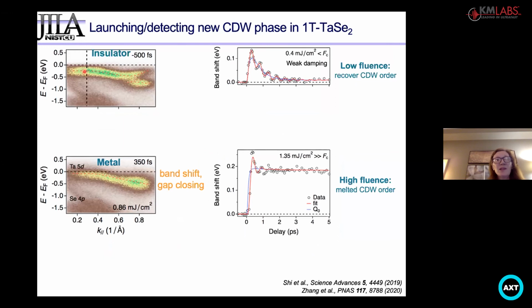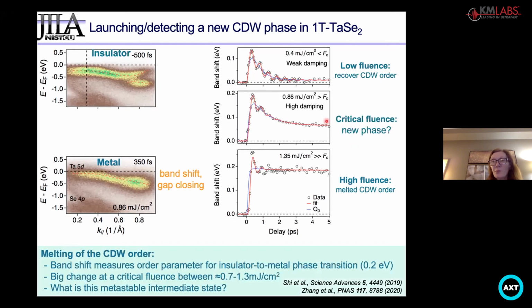So in the insulating state, there's a band gap, and if you take the material and you excite it, you see these characteristic oscillations, and that corresponds to that breathing mode of the Star of David. If you heat the material then with a femtosecond laser, you can drive it above its transition temperature, the band shifts, the gap closes, and this characteristic band shift goes from the band shift corresponding to charge order to correspond to the melted phase. What was interesting though is that by adjusting the laser fluence, we could place the material in any state in between.